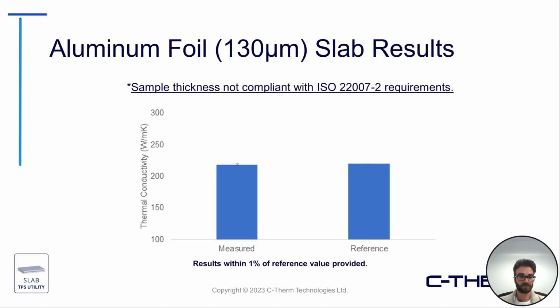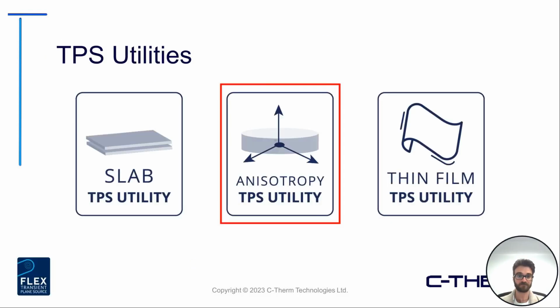And the data that we collected shows some really good comparison to the reference value. I do need to highlight specifically that due to the thickness being much lower than the standard ISO requirements, it's technically operating outside of that standard range. But sometimes, if it's in an R&D setting and you don't really have a valid way of getting results, you can make certain adjustments here. And clearly with this sample type, really good measurements coming in even at about 100 microns in thickness.